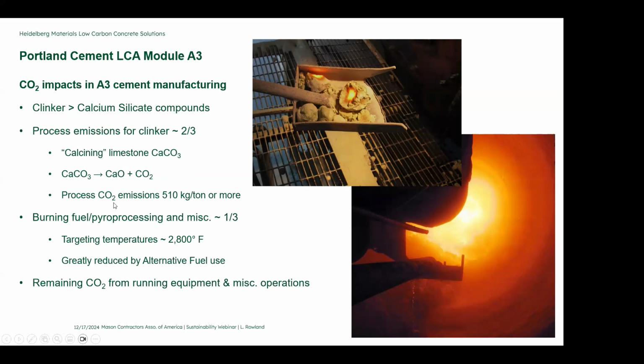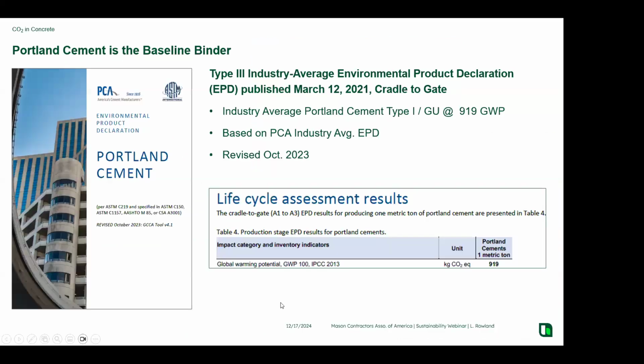These are called process emissions, sometimes called the chemical fact of life for cement manufacturing. So over 500 kilograms per ton of CO2 is released through this chemical reaction. So that means for every 100 pounds of cement you use in your masonry construction, that cement will have released more than 50 pounds of CO2 associated with the calcination. The rest of our emissions are associated with the pyroprocessing, getting the temperatures in the kiln up to the 2800 or 2900 degrees that we need, and then running the motors, electrical power, those kind of things. So most of the CO2 emissions associated with cement manufacture come from this process emission of calcining the limestone.